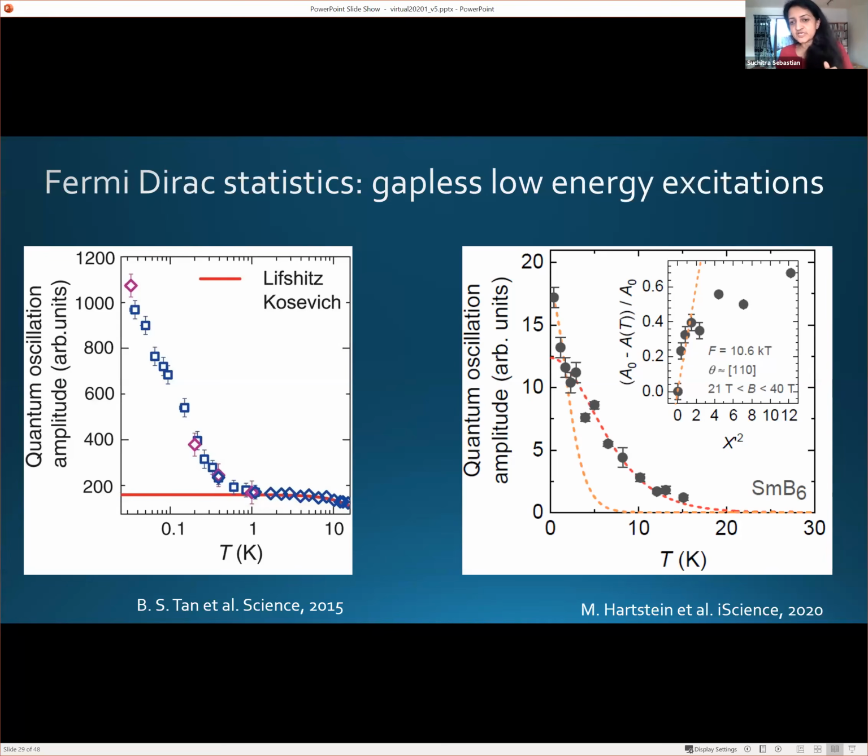From complementary measurements, for instance, there is heat capacity, which is not in and of itself conclusive, given that one could have an impurity contribution. However, there is a finite linear specific heat term, so there's that evidence. I haven't shown it here, but there are NMR measurements of a finite 1/T1T, which again are consistent with states in the gap.